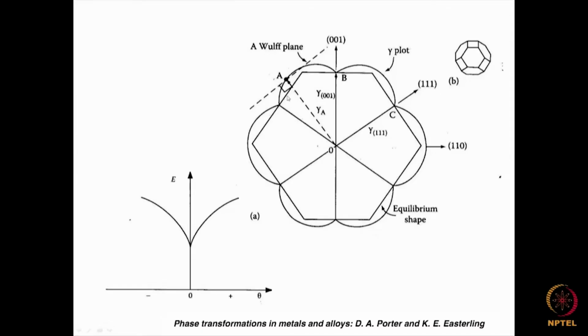So if we take the regions which correspond to the minima in the cusps, and join all of them together, the surface which it includes is the one which it will choose to form the crystal. When it forms the crystal, this is the morphology it will adopt. Essentially, from here there are so many points, and for every point I can find the normal to this vector, which gives the plane. When you take all of these together, the inner envelope which joins them, with respect to area, is the one which it will give rise to; others will be outside of it.